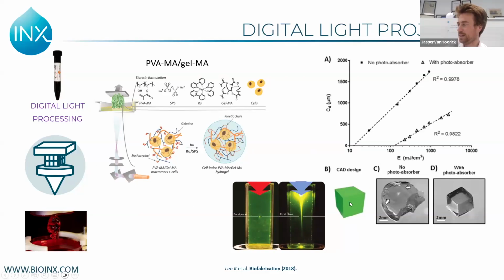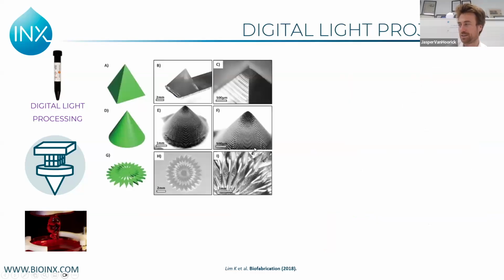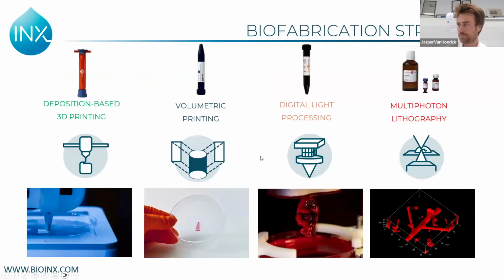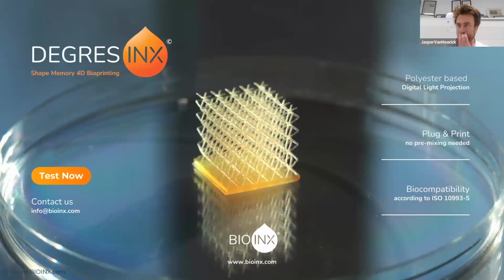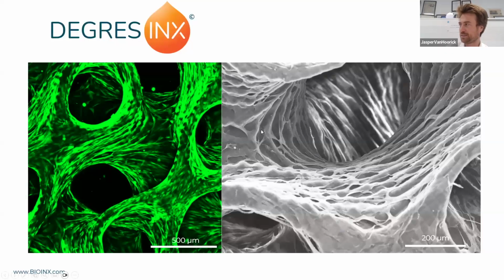Even with a simple structure like a cube, you get a blob after printing because you have a lensing effect of your printed structure. And if you include a photo absorber, you can get these nice structures which translate into very, very fine features. So with this, you can print quite complicated structures. For example, here you see a gyroid scaffold with some cells on top of it.